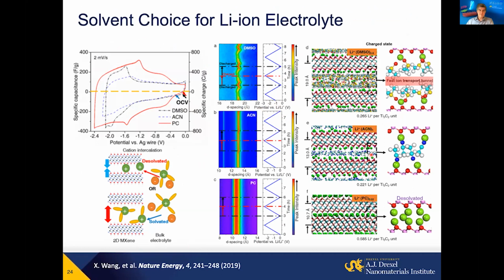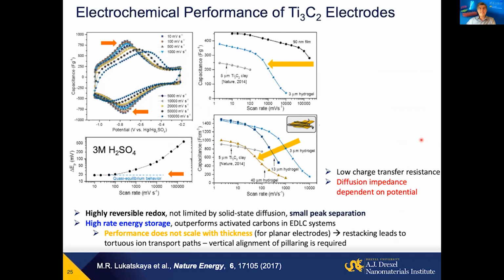when used with lithium salts, will actually go between the layers of MXene together with lithium ions, separating the layers and decreasing the performance. But propylene carbonate, which leads to an order of magnitude less conductivity in solution, actually results in complete desolvation of lithium, and only lithium will be going between MXene layers, leading to a significantly larger area under the cyclic voltammogram and significantly larger energy storage. So whenever we deal with new materials, we need to understand how to handle them. We need to look into their chemistry and electrochemistry. But if we do it correctly, we can get some really exciting results.